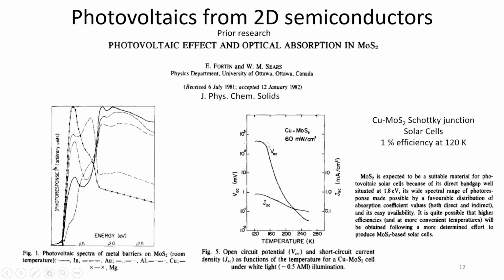And then they did some temperature dependent measurements where they measured the open circuit voltage and short circuit current of the photovoltaic, and they were able to see some values. Their best cells were basically copper MoS2 Schottky junction cells, and they had about 1% efficiency at 120 Kelvin. So they were not very good cells, obviously. But what caught my eye was the very last sentence in the paper: that MoS2 is expected to be a suitable material for photovoltaic solar cells because of its direct band gap, well situated at 1.8 eV, its wide spectral range of photo response made possible by a favorable distribution of absorption coefficient value, and its easy availability.